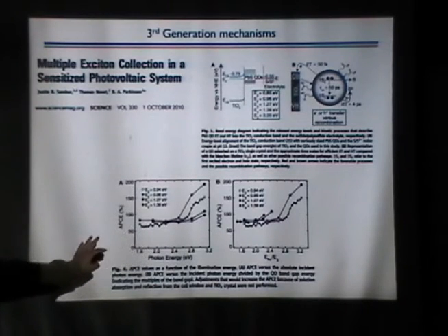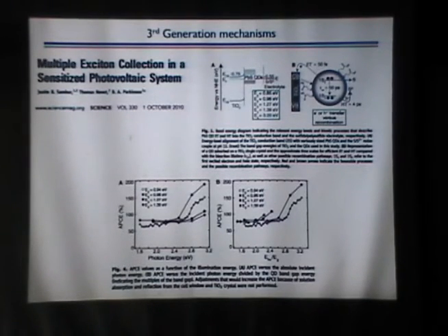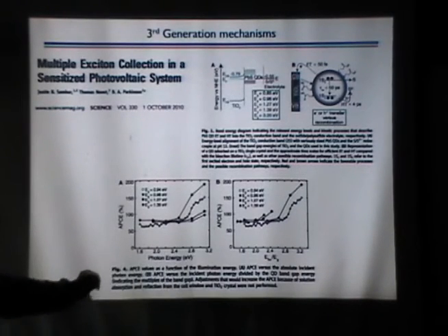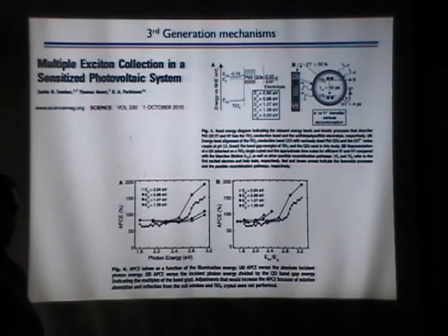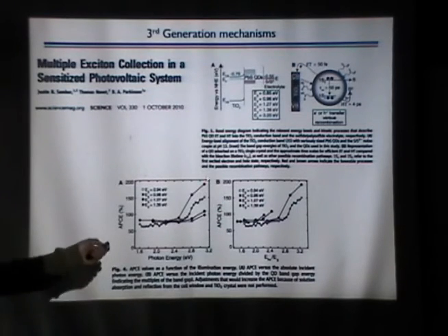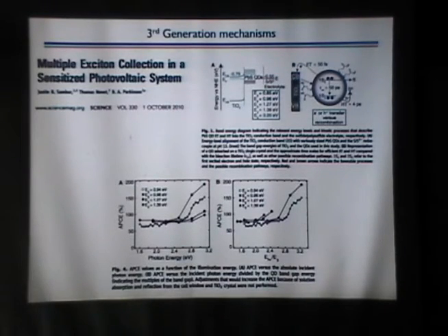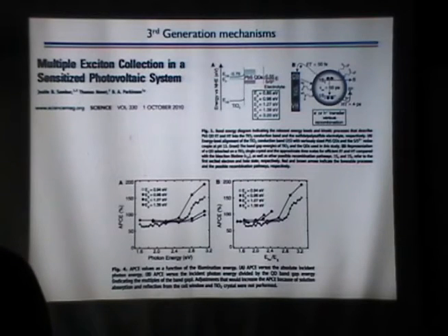This is the first real evidence that you can maybe harness these multiple excitons. It is not without controversy. It's pretty hard to measure accurately the absorption of a sub-monolayer film of quantum dots and to include all the optical effects and optical field effects. So I think that probably more analysis needs to be done, but it's an encouraging sign.